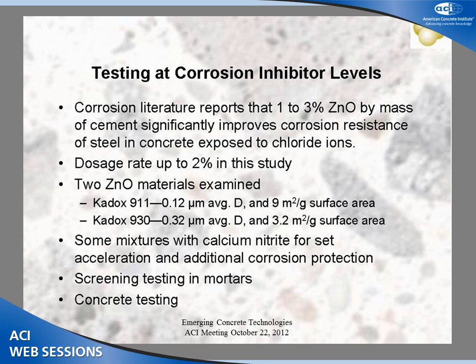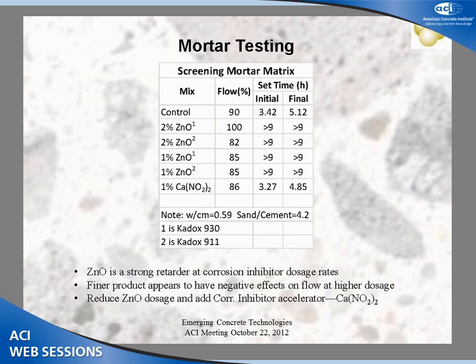So the first thing that was done was some screening tests in mortars. Before actual concrete testing was done, some basic screening tests were done using mortars. There was a control mix. And then there were several mixtures that contained the zinc oxide. And again, the initial work looked at 1 to 2% zinc oxide, dosage levels consistent with using the product as a corrosion inhibitor.